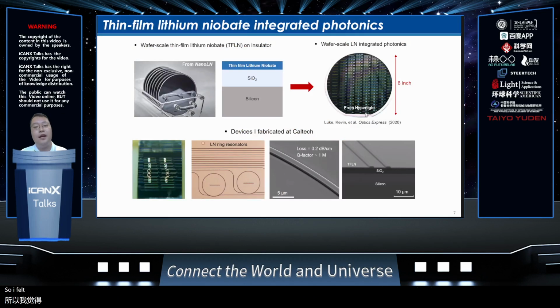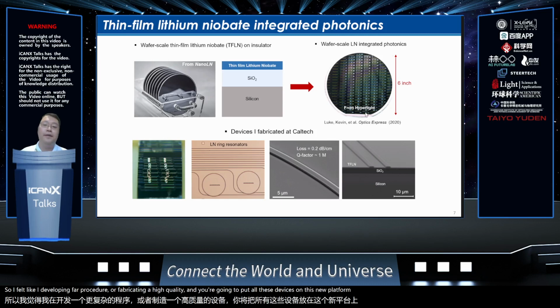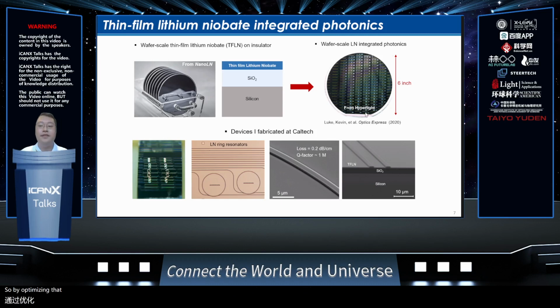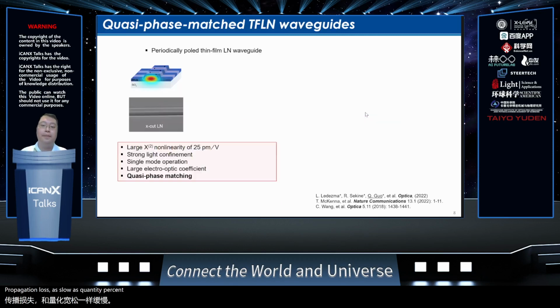At Caltech, I developed an entire procedure for fabricating high-quality integrated photonic devices on this new platform. By optimizing the etching process, we are able to create a very low-loss waveguide with a propagation loss as low as 0.2 dB per centimeter. By making optical waveguides on this platform, we can dramatically increase the spatial confinement of light. This in turn makes the nonlinear interaction between light and the material much stronger.